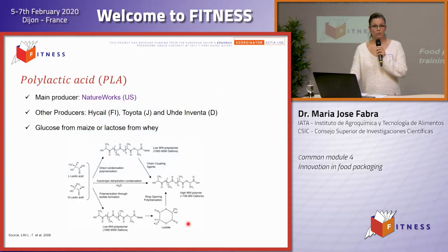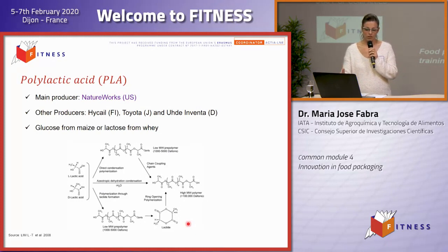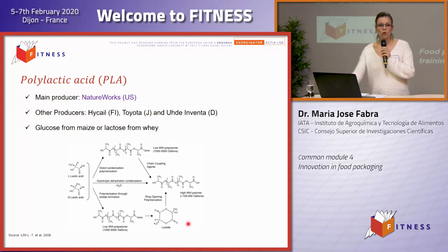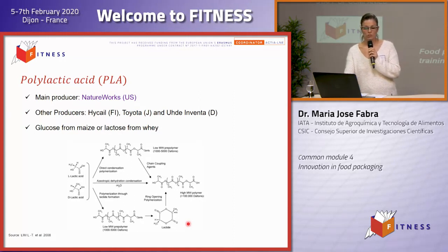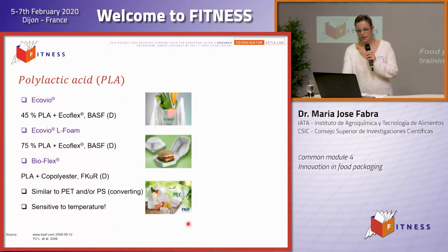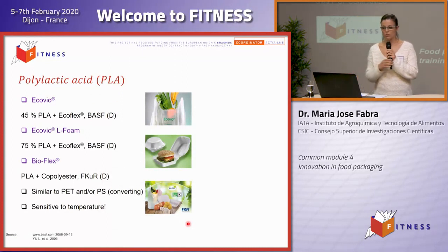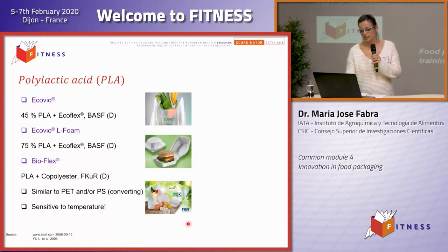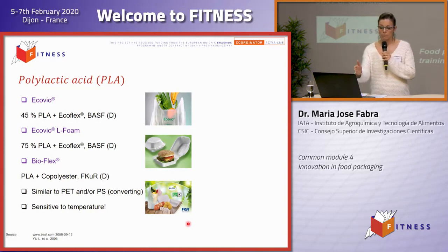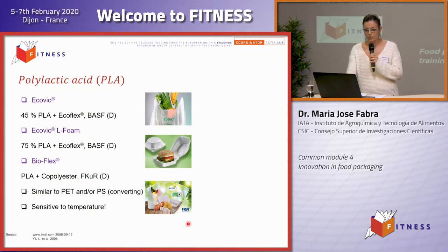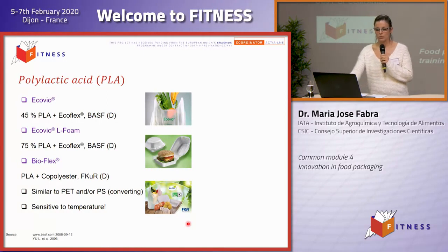The main producer of PLA, which is commercially available, is NatureWorks, but there are others that also produce PLA. And we can obtain PLA from glucose, from maize, but also from lactose from whey. We need lactic acid to produce PLA. There are other PLA-based materials that can be used alone or in a mixture of different biodegradable materials. And the main drawback of these materials is that they are sensitive to temperature.